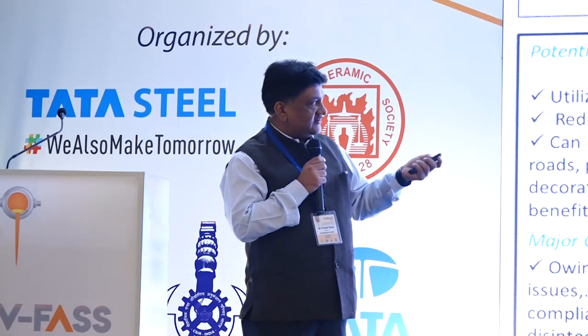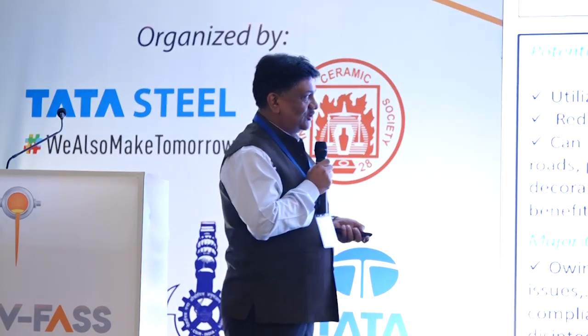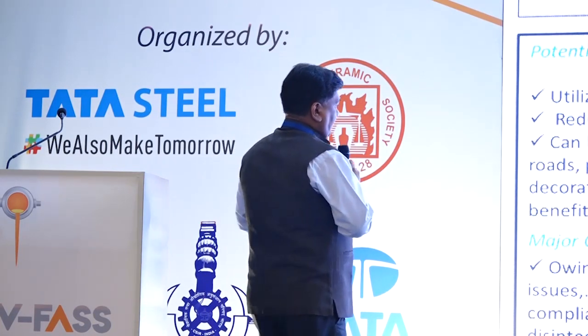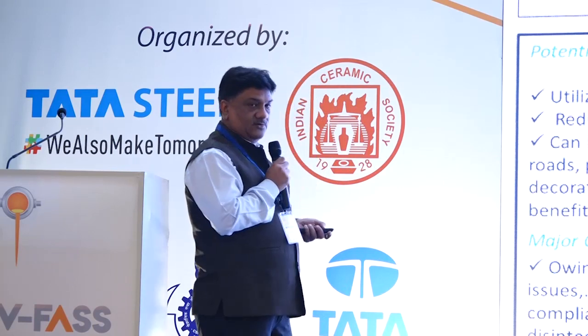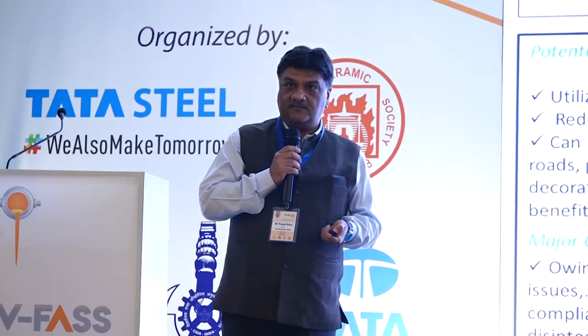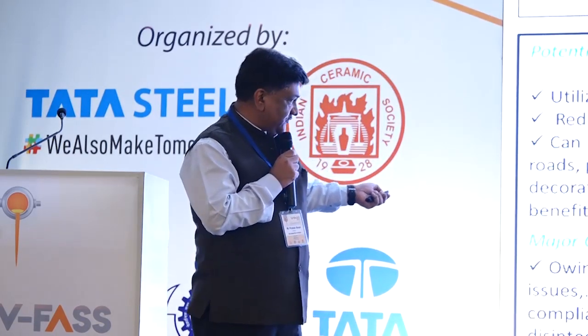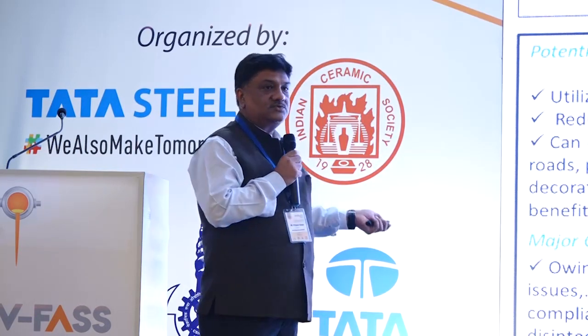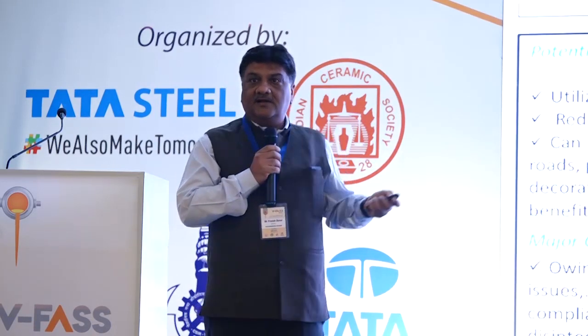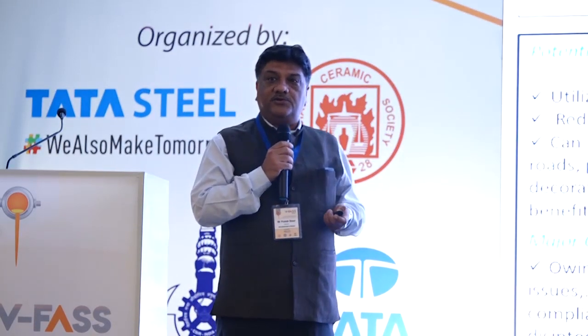Replacing it as an aggregate, of course, we have certain limitations. The codal provision says we should not use it for reinforced cement concrete as per IS 383. But this can be done. Believe me, what we have done, the unsoundness test was passing at less than 1%, whereas the P2O5 is the major challenge which we found. If we can adopt some process parameters with some technologies, definitely it has a very high potential to be utilized in concrete as an aggregate, replacing fine aggregate.